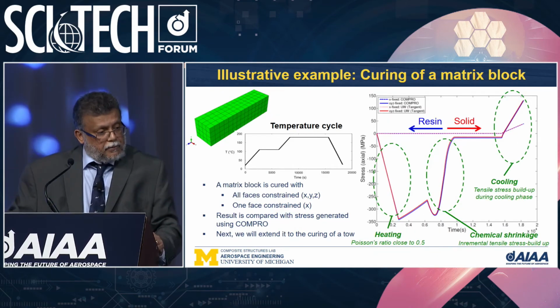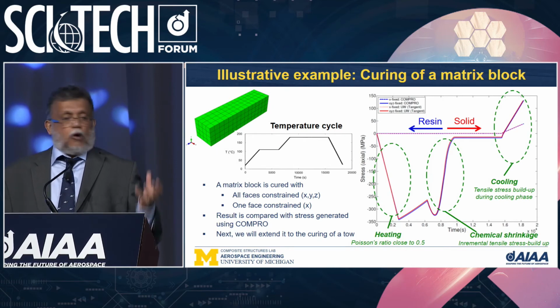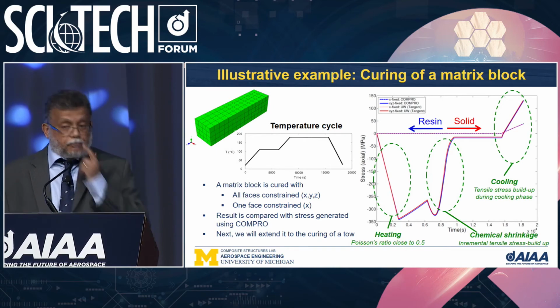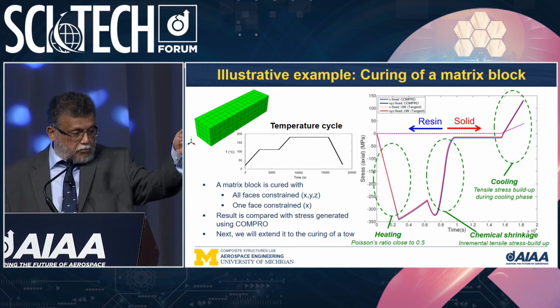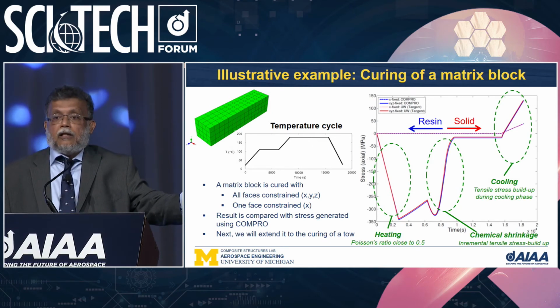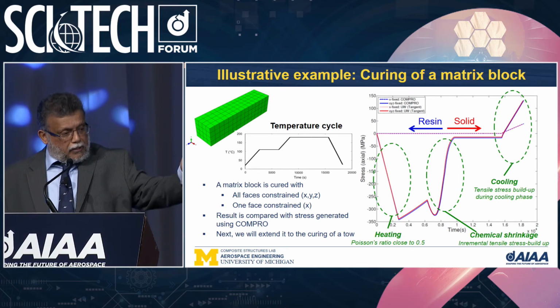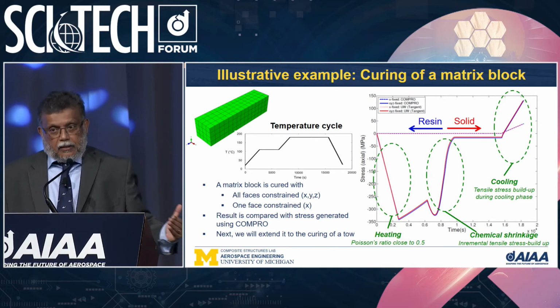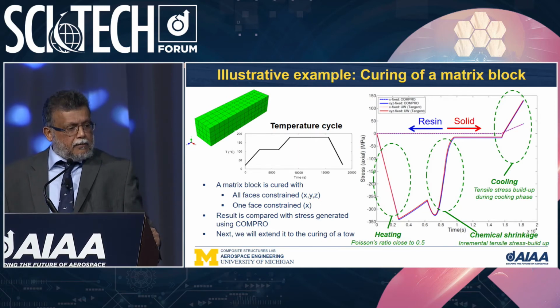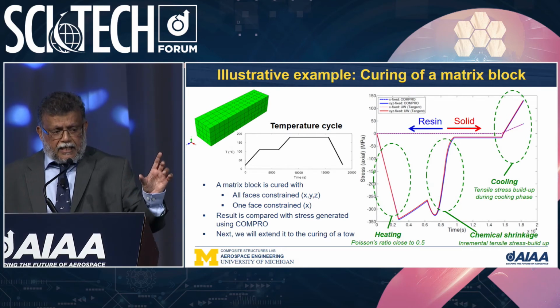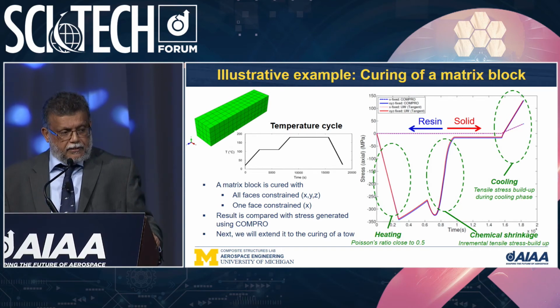Here's an example of curing a block of resin with that temperature cycle. Initially, you get stresses developing in the resin, they relax, and then during the final drop in temperature, shrinkage strains set in and the block solidifies. So you get tensile stress buildup during the cooling phase, which is the final phase in your cure cycle.